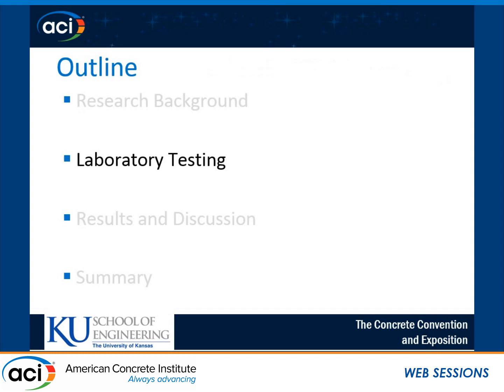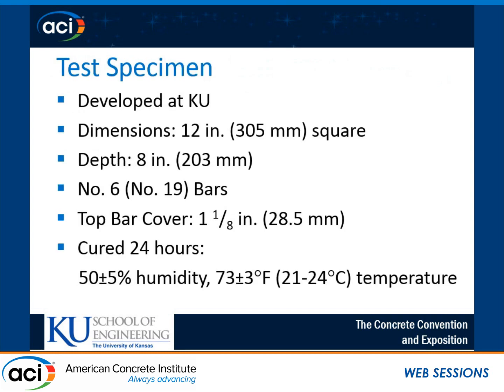Now getting into the laboratory side of things. So this is a test, again, that we developed at KU to qualitatively compare different crack reduction technologies against a 100% Portland cement mixture in terms of settlement cracking performance. Geometry of these specimens, we cast 12-inch by 12-inch by 8-inch deep beams. We cast those with a single number 6 bar with 1 1/8 inch of cover over the top of that. And after casting, we place these specimens in an environmentally controlled room for 1 day of curing, 50% plus or minus 5% humidity, and 73 plus or minus 3 degrees Fahrenheit.